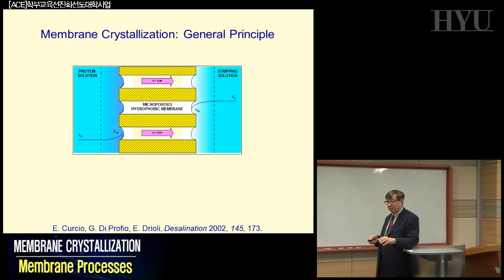A lot of proteins are present, bound in membranes. We are learning, and now we know today, that the role of the membranes is much, much more than just helping the evaporation. Because the membrane itself, with the surface energy of the material you are forming, with the pore size distribution, and with the creation of interfacial phenomena, etc., is contributing much more than expected to the final performance of your membrane crystallizers, as you will see.